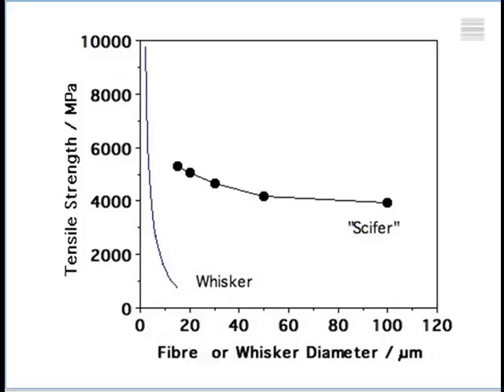The problem is that if you get strength by deformation, then you will make wires or very thin sheets. Okay? You cannot make large, big chunks of iron. So just to give you an idea of the scale of this steel wire, when we look at